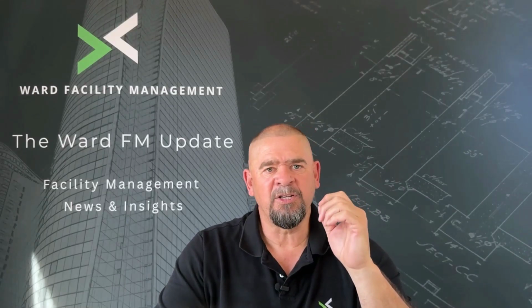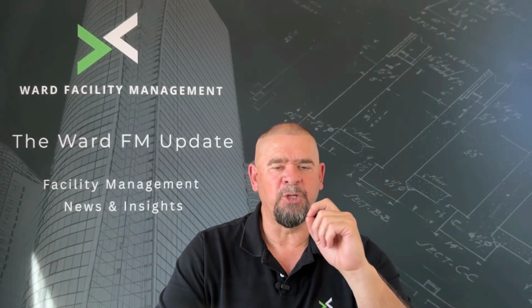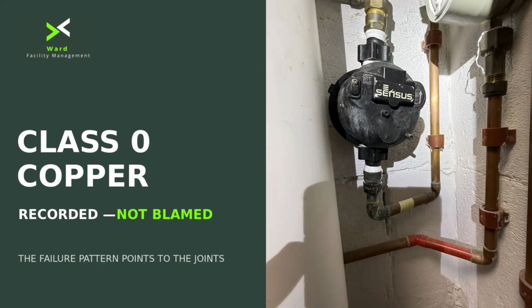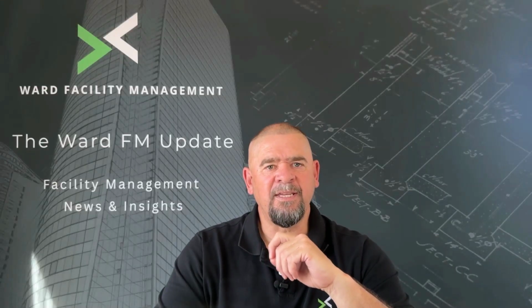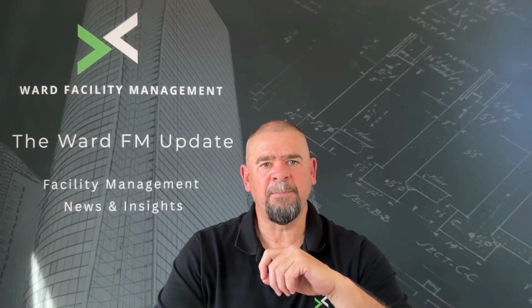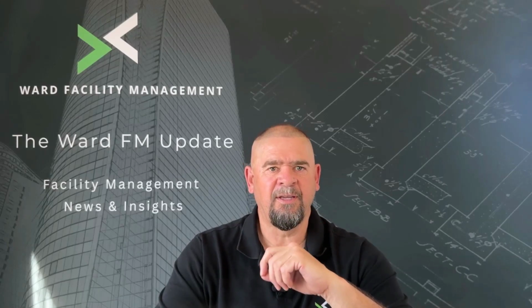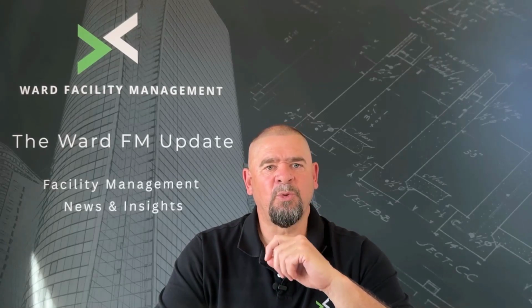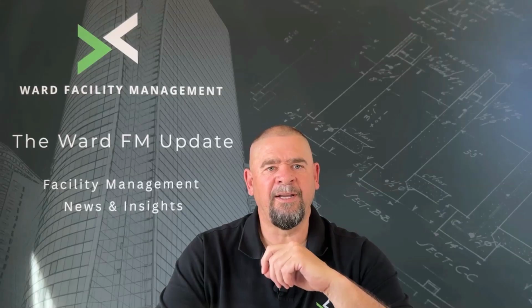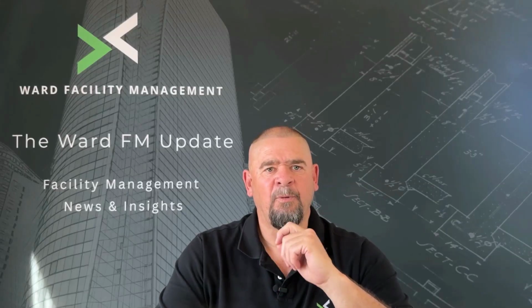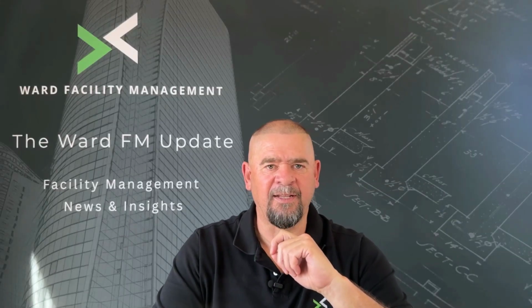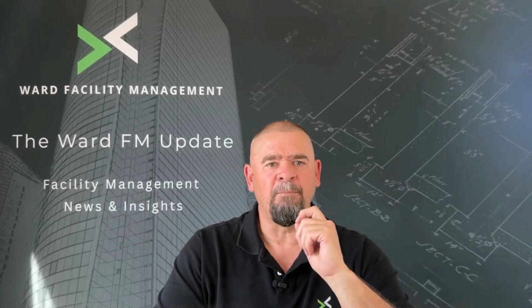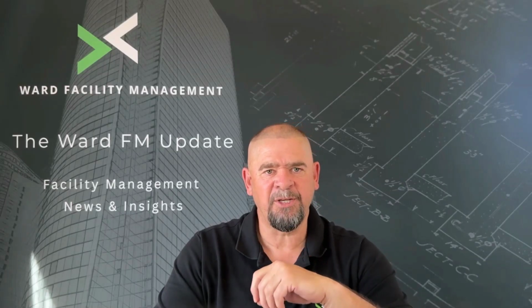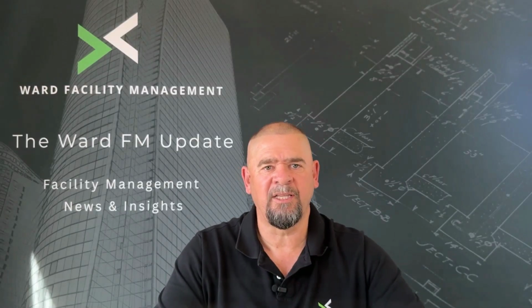At this stage, the corrosion pattern points more strongly towards the way the joints were made. Whether the flux was properly removed, how the different materials are connected, and whether small leaks have been allowed to continue. The age of the installation is also important. These pipes were installed approximately 6 years ago. A correctly specified and properly installed copper plumbing system should normally provide a considerably longer service life. One leaking joint may be an isolated defect, but several reported leaks combined with similar corrosion and multiple connections suggest a wider installation quality concern.